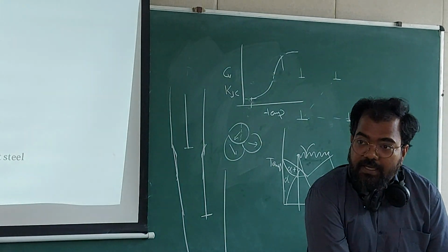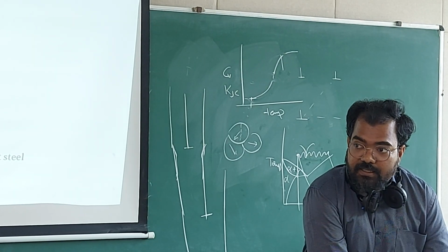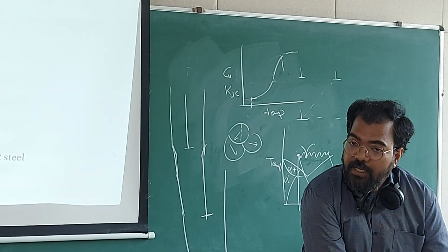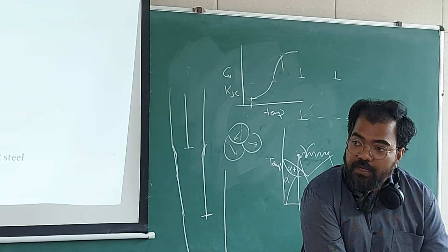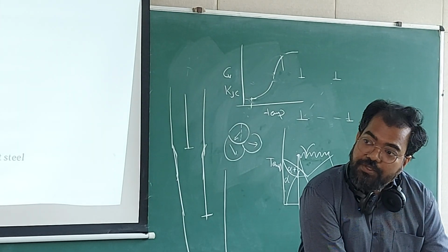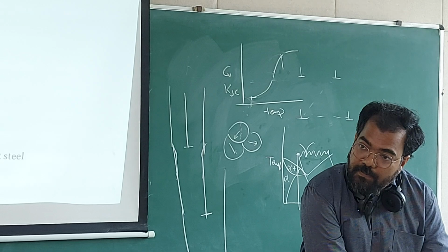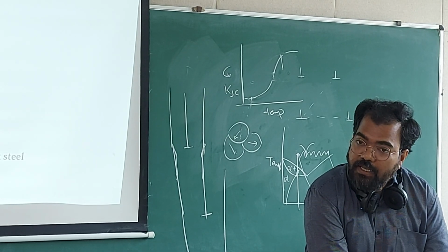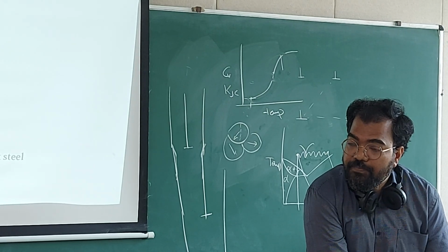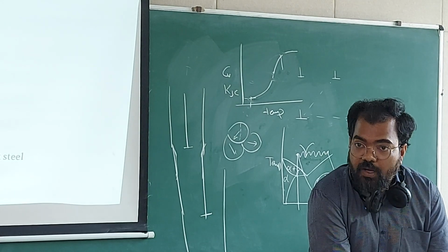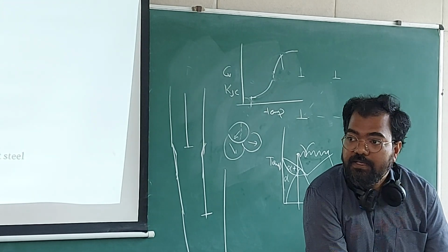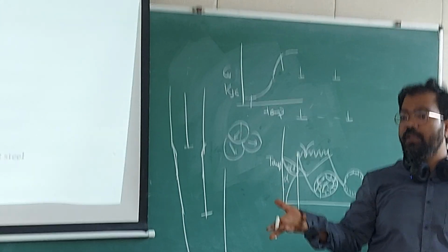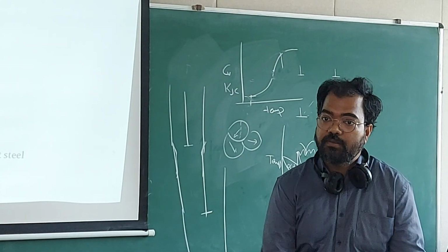But in a very high cycle fatigue case, the crack develops from inside, not from outside. Why? Because the damage has been happening for the whole duration of 10 to the power 10 cycles. It would have failed in 10 to the power 8, 10 to the power 7 cycles if the load was higher. The load is smaller, and the concept of endurance limit said that you can go to an infinite number of cycles and things will not break, but that's just stupid.